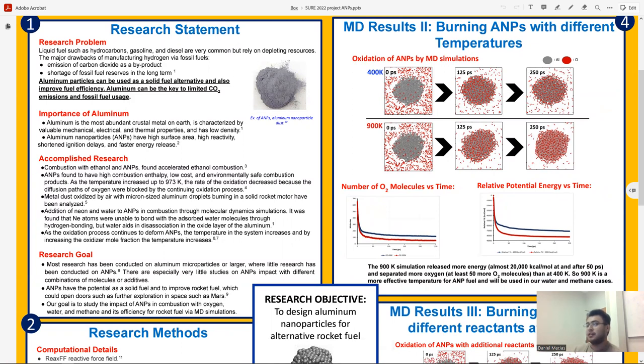But it's visible that at 900 Kelvin, you could see that more of the oxygen molecules were absorbed by the aluminum as opposed to the 400 Kelvin. Just by looking at this, it was clear that by using a high temperature system on aluminum nanoparticles, the system does react better. We also had two different graphs, one explaining the number of molecules absorbed and the relative potential energy versus time. The blue line represents 400 Kelvin and the red line represents 900 Kelvin. The gap demonstrates how many oxygen molecules were absorbed. It's clear that using the system on a high temperature does in fact create a more efficient system. At 900 degrees Kelvin, the system did release more energy as opposed to the 400 degree Kelvin. Also, the amount of potential energy that was released was much greater than the 400 degrees Kelvin.